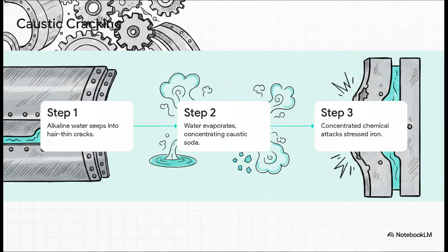Step 1. In these high-pressure boilers, leftover sodium carbonate from earlier water softening treatments gets hydrolyzed into sodium hydroxide, which is caustic soda. This highly alkaline water quietly sneaks into microscopic, hair-thin cracks in the boiler's riveted joints through capillary action. Step 2. Because the metal is blazing hot, the water inside that tiny crack evaporates, leaving the caustic soda behind. This cycle just repeats and repeats until the chemical is incredibly concentrated.